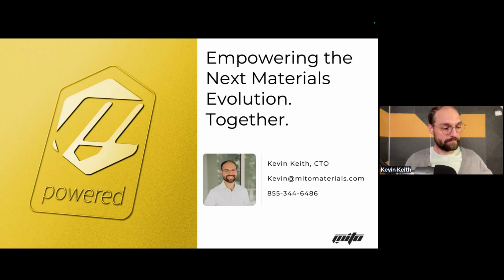From a chemistry perspective, how do your graphene materials differ from the structure of coal and the properties that they provide? That comes down to, okay, a metallurgical lesson a little bit. Metals have certain grain structures, like a BCC type thing, where you have either a crystalline or more of an amorphous type structure. Same thing goes with polymers. You either have essentially a pile of spaghetti noodles or you have a very ordered system. Same thing can happen with graphene. Graphene can come in this very crystalline, very jagged form, or it can come in more of an amorphous, crumpled, very pliable form as well.